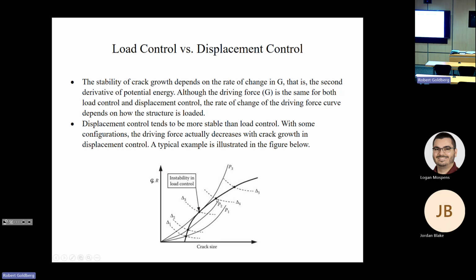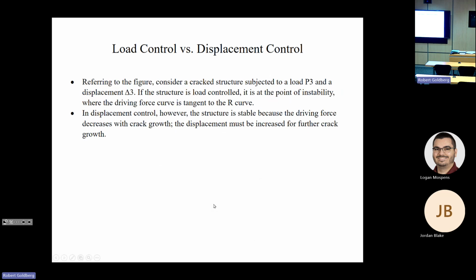So the R curve is determined experimentally, but the trick is usually when we do experimental tests, we do displacement control most of the time because displacement control is a much easier test to do than load control. A lot of times it's hard to do a load control test. Since most of the common test specimen geometries exhibit falling driving force curves in displacement control, you can get an awful lot of stable crack growth. And if an instability occurs during the test, the R curve can't be defined beyond the point of ultimate failure. Okay.